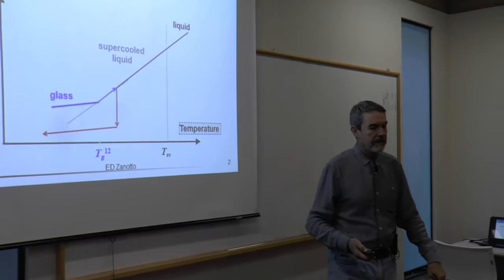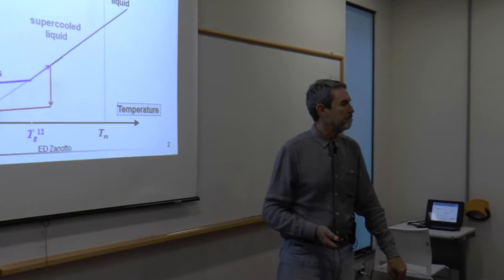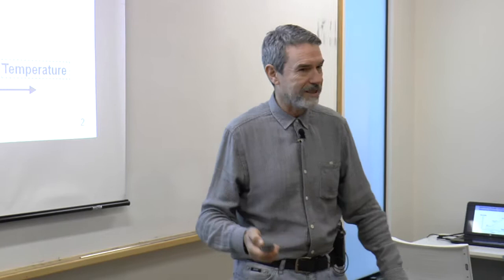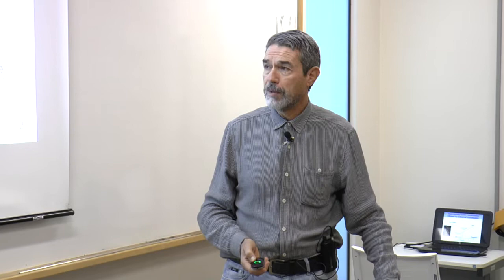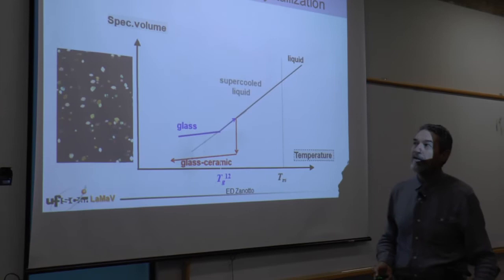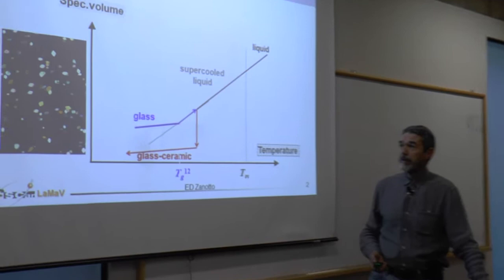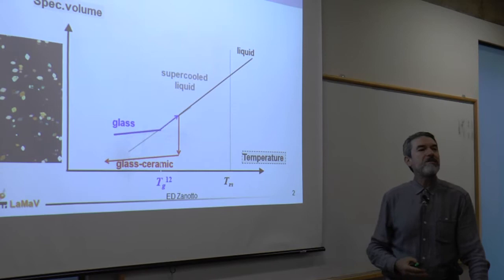But we prefer to work here where the nucleation kinetics can be measured in a matter of seconds to hours. That's the typical laboratory time scale that we use here in the lab, and most people use. So this is a micrograph of the so-called Drosophila of glass crystallization studies. Lithium disilicate is a very good model system to work with nucleation and crystal growth kinetics because it's not extremely fast and also not extremely slow.